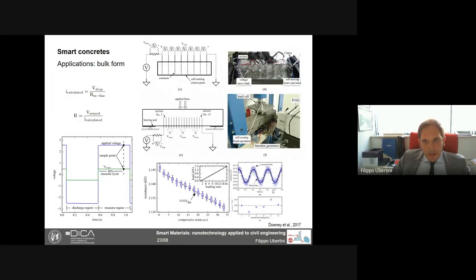Another application we have proposed is when we use the smart concrete in bulk form. So the whole material, the whole element, maybe a critical part of the structure, like a node or something like this, is fully made of smart concrete. Here you see an example on specimens like the one on the top with different pairs of electrodes, or on a beam under 3-point bending. And we use the biphasic DC approach to do multi-channel readings and remove polarization.